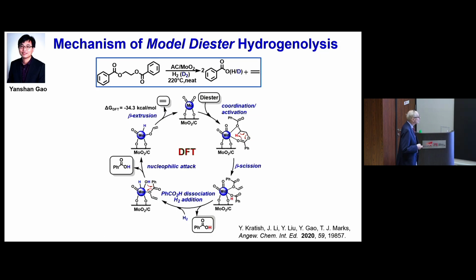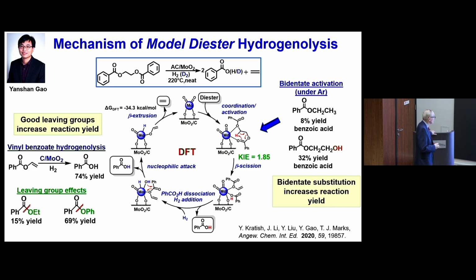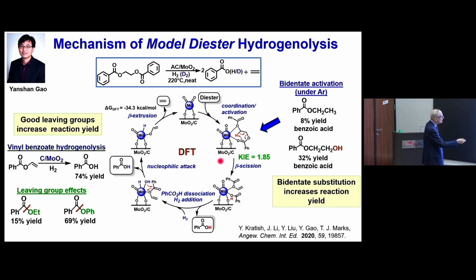Well, what more can we learn about this catalyst? I won't go through the mechanism in detail. This is Yanshan Gao's work. He's now at SIOC. But basically, let me maybe show you a little more. The mechanism involves coordination of this diester, work that Yanshan did, and then the DFT. The next step is to cleave a carbon-carbon bond, and we get a kinetic isotope effect, which is two ways to check your DFT calculation.